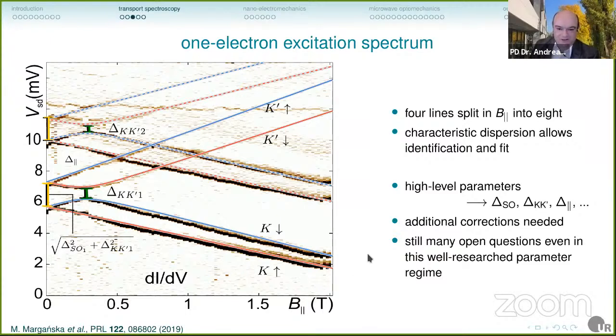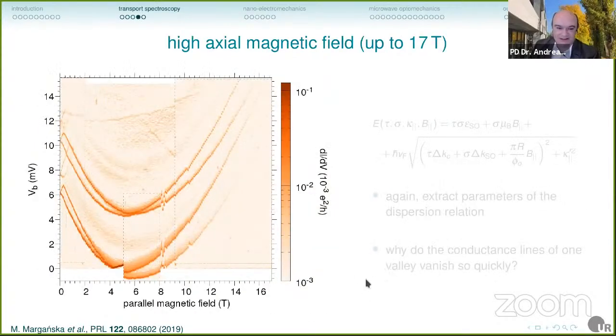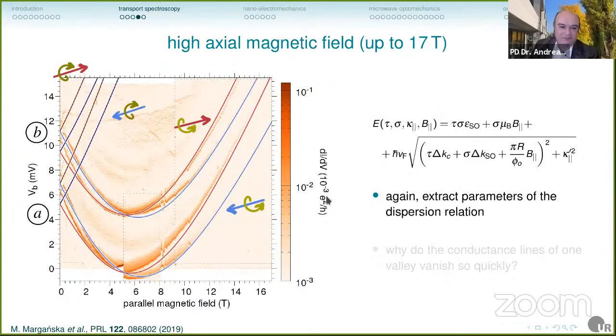It gets more interesting if you don't go to 2 Tesla, but to 17 Tesla. Then you can see that you basically apply a flux through the nanotube, and you are shifting your cuts across the Dirac cone. So this is basically tracing the Dirac cone of the graphene. Again, we can apply fits. Again, we can extract the parameters of the dispersion relation. But here, there are even more puzzling things left.